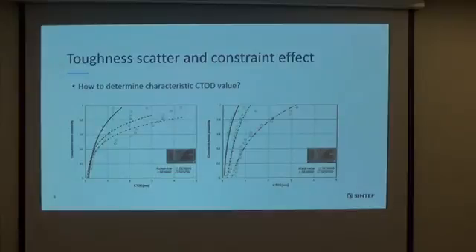The first thing is toughness scatter. I'm talking about brittle fracture. If you test your material at minus 60 degrees, you're going to have a lot of scatter in your fracture toughness data. So the question is how to determine a characteristic CTOD value. In the end, the designers need one value to tell them what value to use. If you test one series of specimens and get 20 points, what is the value you can use? This is a question directly from our designers.